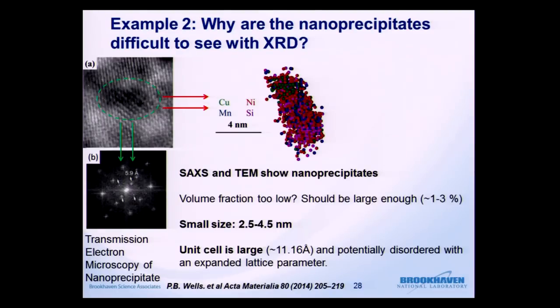So why are these nanoprecipitates so difficult to see with X-ray diffraction? We know they're there, right? We measured them with SAXS. I showed that in the first example. And we also have transmission electron microscopy of the nanoprecipitates, so we can see them in microscopy. So why don't we see them with diffraction?